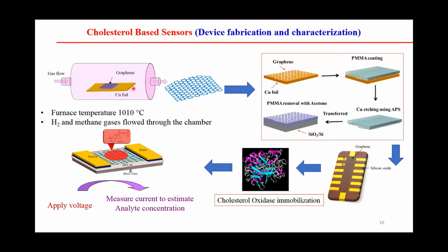So if you want to make a FET, or field effect transistor, you can transfer this graphene onto any desired substrate by using this method. Here the graphene is on the copper foil. We can spin coat a thin layer of a polymer, here polymethyl methacrylate, and after that we can etch the copper foil using ammonium persulfate solution, and then transfer it onto the desired substrate. By doing that, we can transfer our graphene film onto any kind of desired substrate.